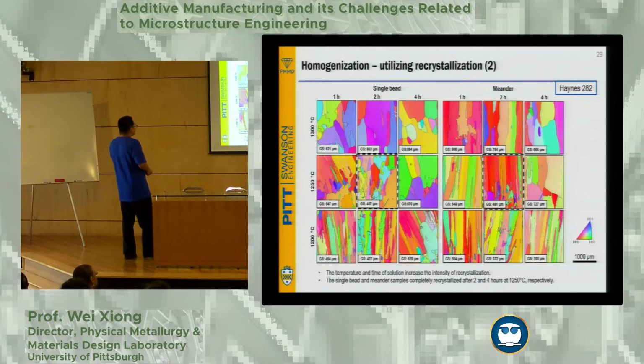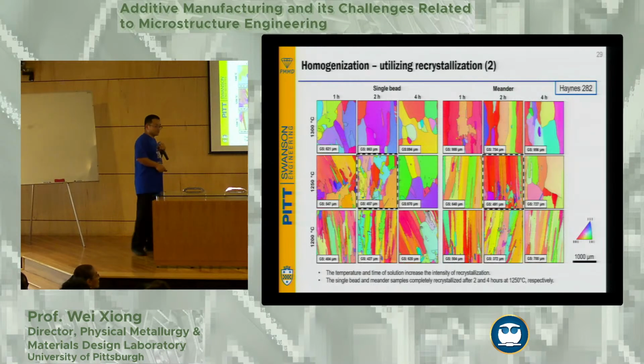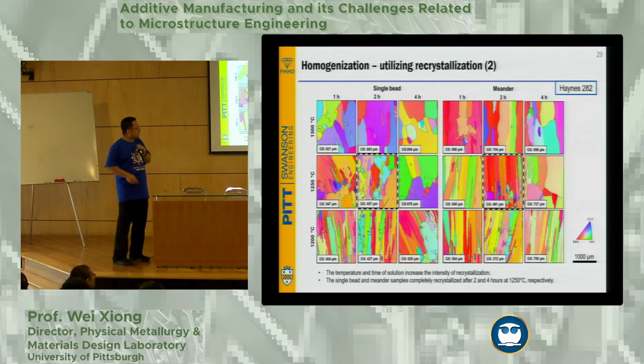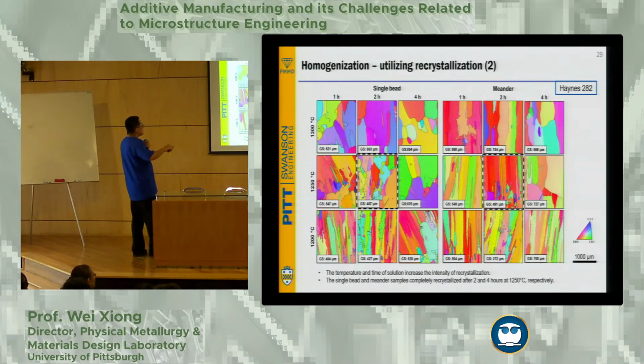So what we did is check in with different temperatures. We also want to promote some recrystallization process. What we did is different temperature, different time. And behind this, we were checking segregations and used Thermo-Calc and Calphad to predict some of the reasonable times for homogenization and guide us to do experiments. That's the reason behind this choice of temperature. I just won't discuss this here.